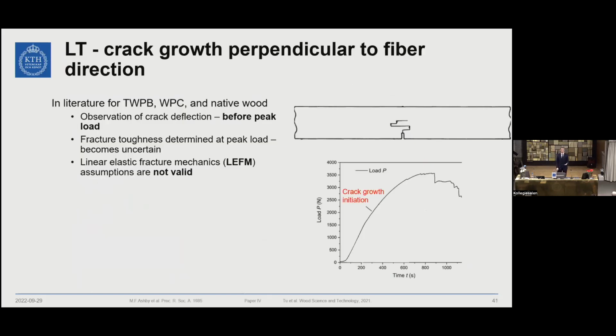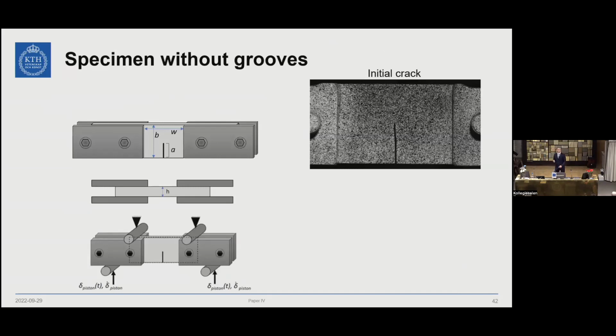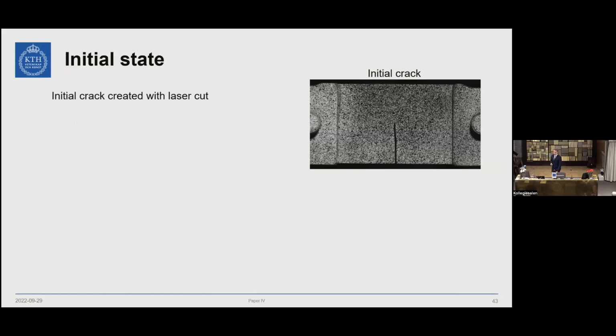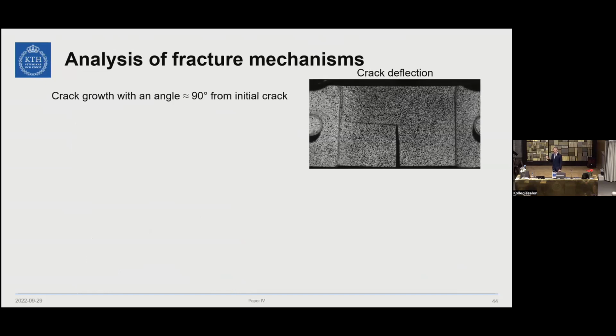In their experiment, the crack path was not straight, and this is quite common in the literature when you read about wood, that the crack does not actually grow in a straight manner. But we want to investigate why it is not. Why is the crack path not straight? So I used the same specimen setup as before, as for the weakest direction. We initiate the crack with the laser cut, and we subject it to a load, and we can see directly that there's a crack propagation along the fiber direction.